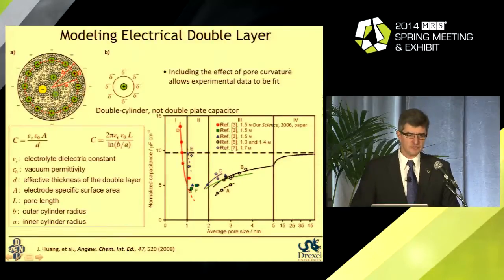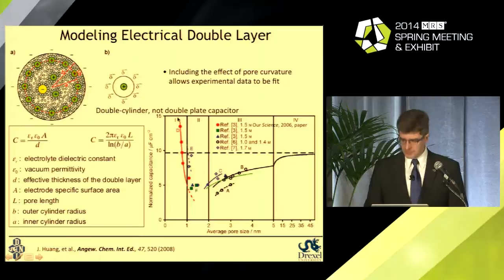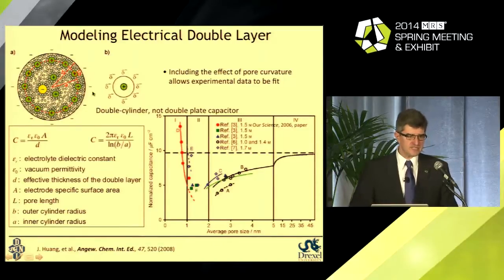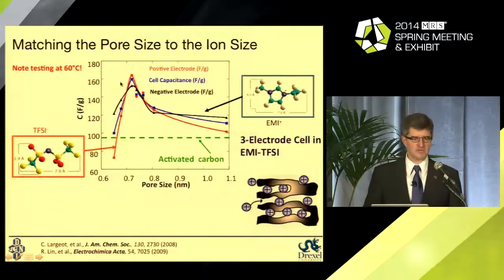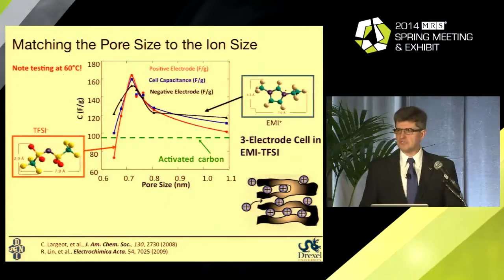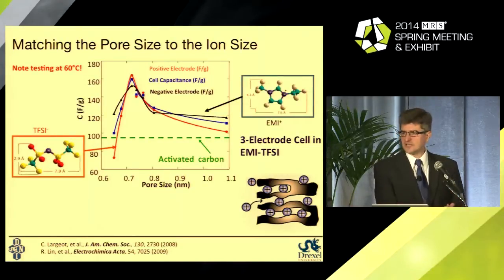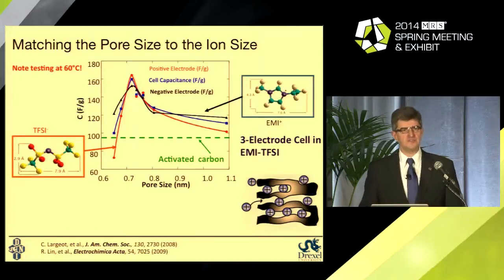Modeling very quickly showed that really this is exactly what is expected for small pore sizes, in case we consider not mesoporous materials with ion solvation shell, but ions in micropores here. And there has been a tremendous amount of modeling and simulation and atomistic modeling done over the past few years to understand adsorption of ions and confinement of ions at the surface and in porous materials here. An example I show you here is actually the next step that we did, trying to move from solvated electrolyte to ionic liquids. Ionic liquids, room temperature ionic liquids, are electrolytes which are basically organic salts liquid at room temperature here.